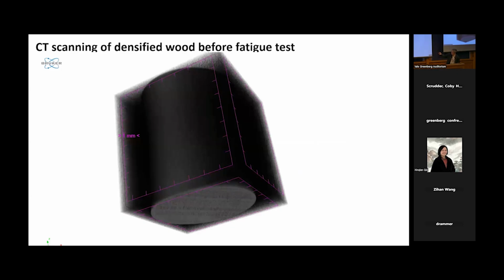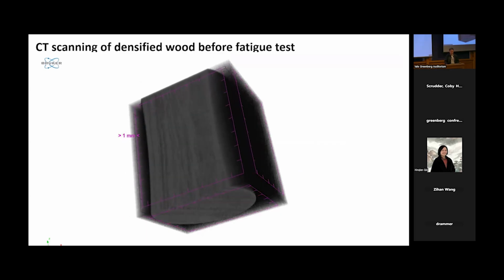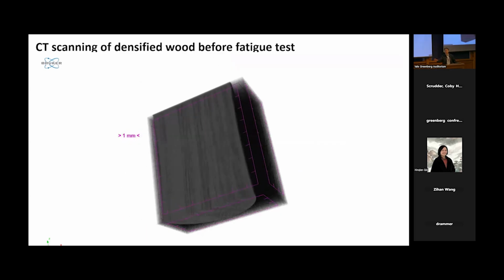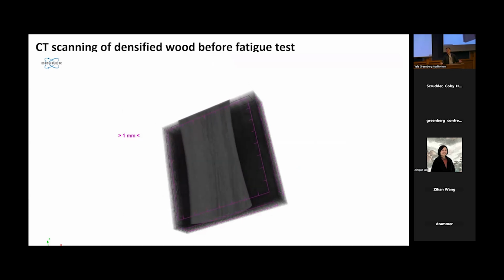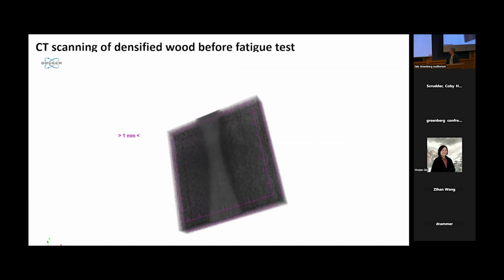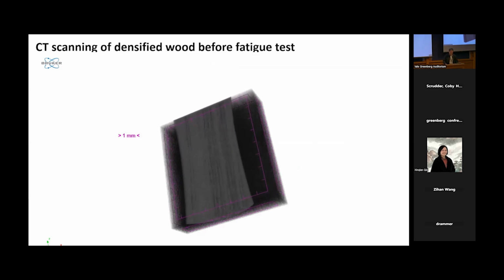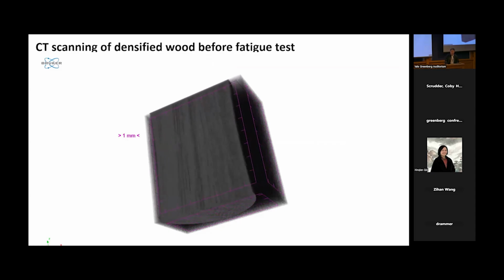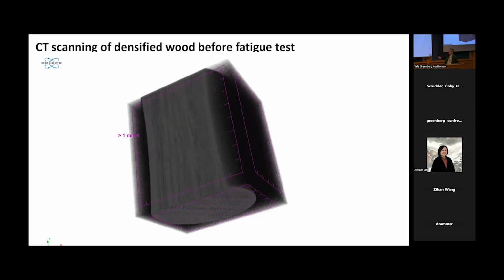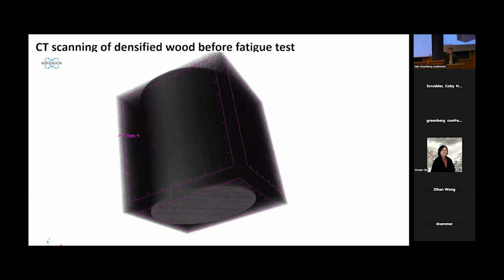This is the sample before the test. So basically, CT scanning lets you see what's really inside, because we don't want to break the sample, as that will introduce unnecessary damage to the sample. As you can see, the scanning goes from this direction, this is like the cylinder, you scan in this direction, you see everywhere in the cross section, and you don't really see any damage. This is before the fatigue test. It shows that the sample we made is of good quality.